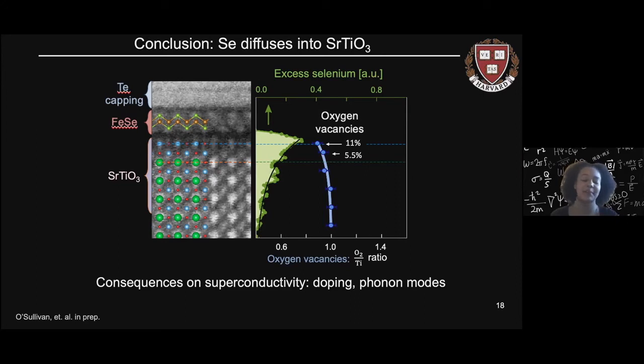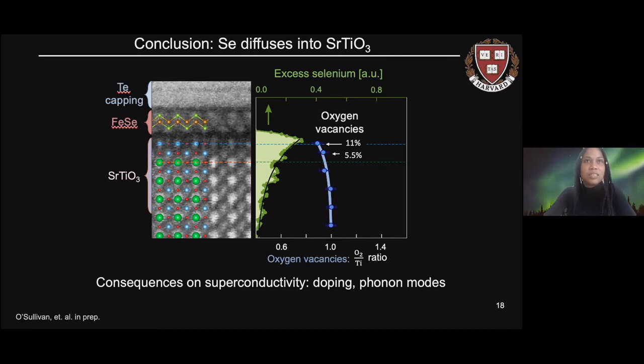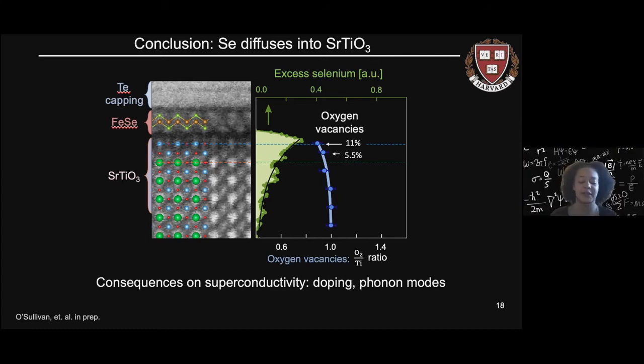So we cap the iron selenide monolayer with tellurium primarily because of how we prepare the material for measurement. Especially for scanning transmission electron microscopy, as well as for atom probe tomography, we use a process called focused ion beam nanomilling, which allows us to essentially shape the material into the correct shape for measurement. And so by having this large tellurium capping layer, we're able to do that shaping without damaging the monolayer of iron selenide itself or the bulk of strontium titanate. And so the capping layer really provides that extra protection and room for us to be able to shape the monolayer and prepare for measurement.